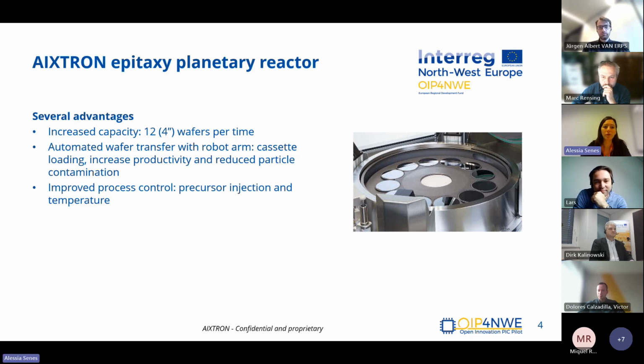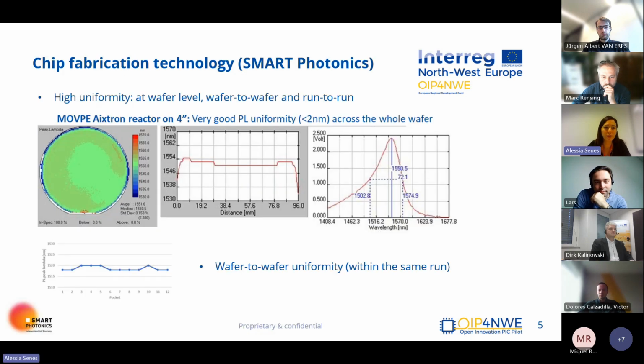This reactor also allowed for improved process control. In particular, precursor injection and temperature can be very stable. So the process can be finely controlled and can be very stable. And due to this, it was possible to achieve high uniformity, both at wafer level, but also at wafer-to-wafer and run-to-run level. Here you see the PL wavelengths across the 4-inch wafer.